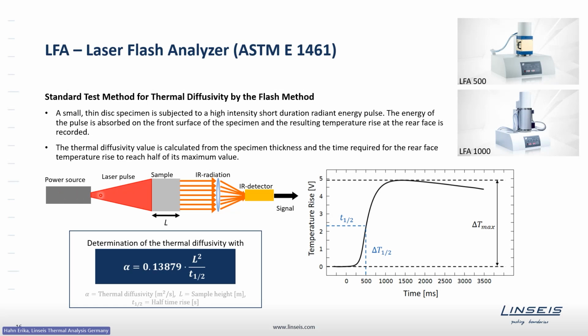The power source shoots a short, high-intensity pulse towards one side of the sample, and we look at the rear surface with an infrared detector and collect a signal, which looks like that, where we see the temperature rise with time and then the decay of the temperature just due to heat losses. Out of that curve, the thermal diffusivity is calculated using also the specimen thickness and the time required for the rear face temperature rise to reach half of its maximum value. So this you can see here, graphically illustrated, where we find out half of the maximum and then use the time of that to be able to determine the thermal diffusivity according to this formula, where we have a constant, the sample thickness, and this half-time rise.